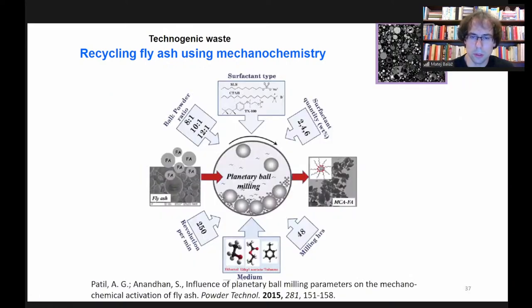This is an example from the work about treatment of fly ash, where the authors played with the different milling parameters, like, for example, milling time or rotation speed, or ball to powder ratio, which the authors played with a little bit. And also the surfactant quantity was changed here. And as a result, they came up with different fly ash, with different properties, of course, and they devoted the rest of the study to the proper characterization of the mechanochemical effects.